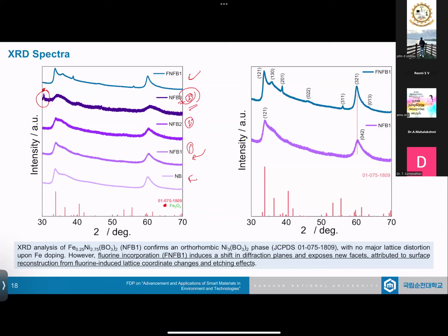So what happened with respect to our survey and with respect to our plan, the same thing happened. Compared to the iron doped nickel orthoborate system, more planes were exposed with respect to fluorine incorporated one. We also saw a shift in the peak where again that also suggested that the surface has been extensively altered because of the incorporation of fluorine. But we have to ask the question now, how did the fluorine do it? What happened really there? And will this give a good output with respect to our requirement?